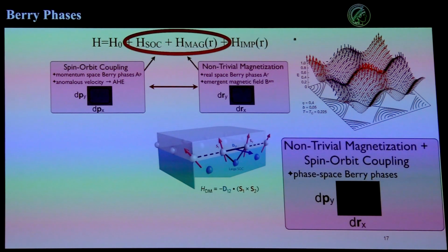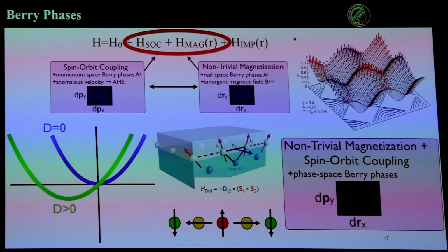The other thing you can see is that as you mix these two things, the magnetization and the spin-orbit coupling, this is where you get these phase space Berry curvatures. So in momentum space and real space, you get the Dzyaloshinskii-Moriya interaction, which is not a transport response, but a ground state property. And this comes from what's called a ground state spin current between the atoms. So it's not a real current, but you're exchanging the electrons, and this causes the DMI. This causes spins to point perpendicular, as we said, and create spirals. And what it does to that quadratic equation is just shift it down.